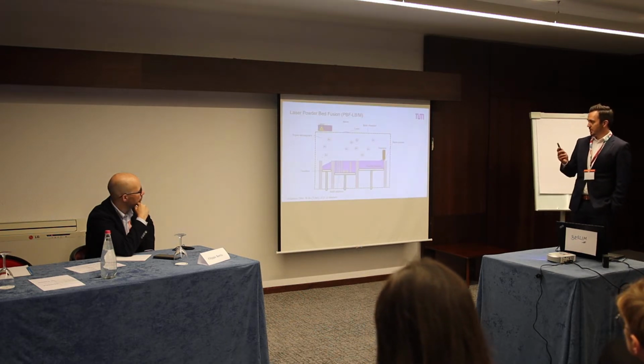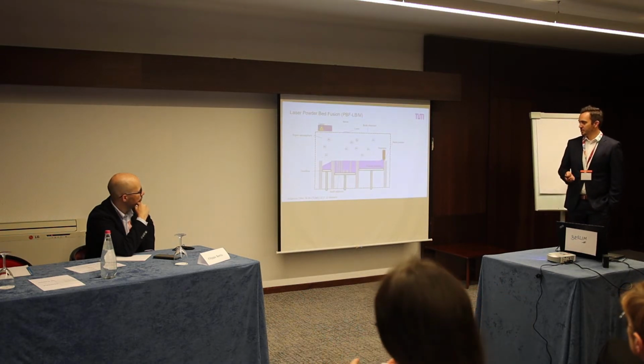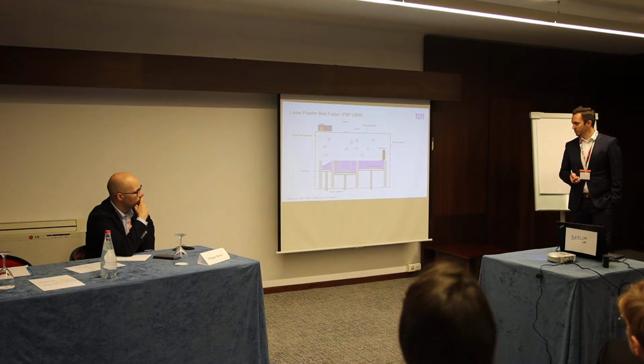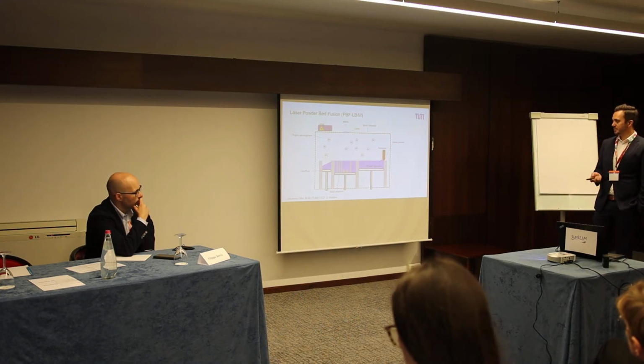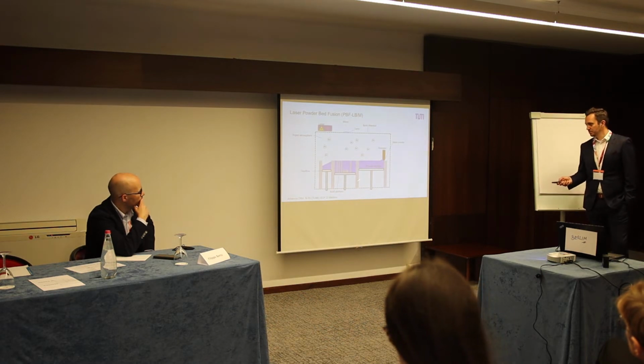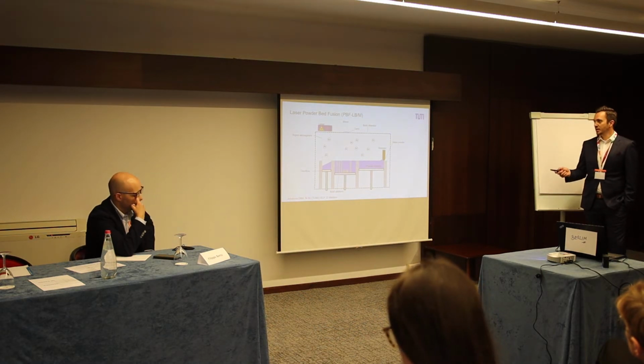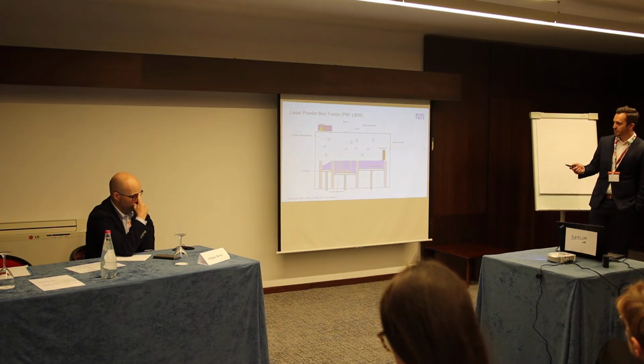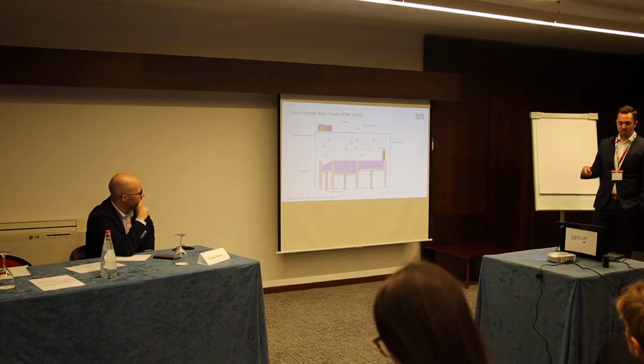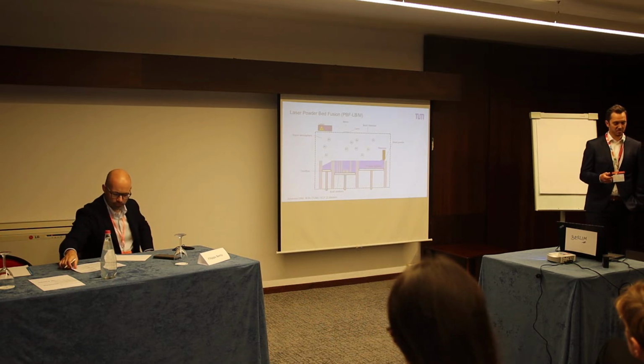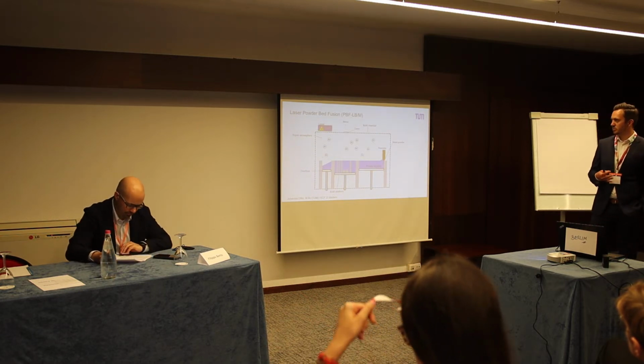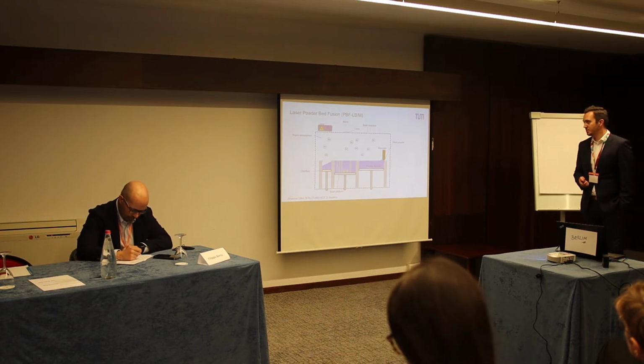So this is basically the build chamber of the laser powder bed fusion machine. We have a hermetically sealed build chamber filled with argon. We've got our recoater here, our powder storage, the build platform, and the overflow container. Here on the top, we've got our laser with a mirror, guiding the laser beam into the right area on the build platform, and the F-theta lens is focusing the beam to the right dimension, usually 100 to 200 micrometers in diameter.